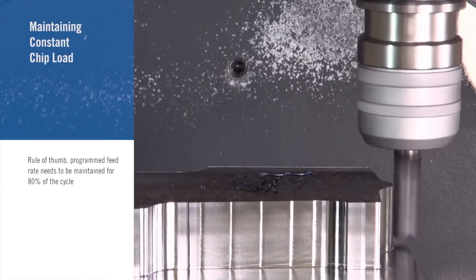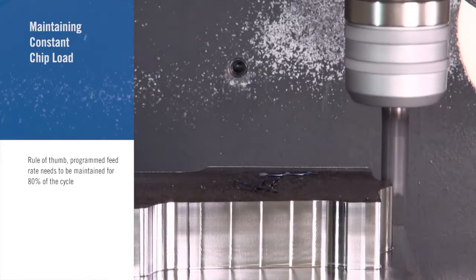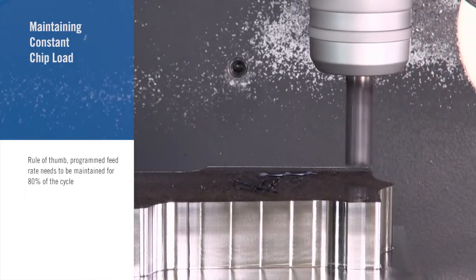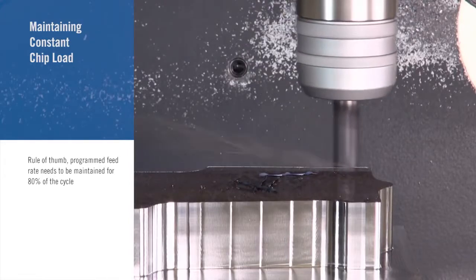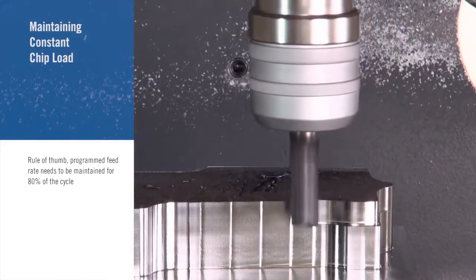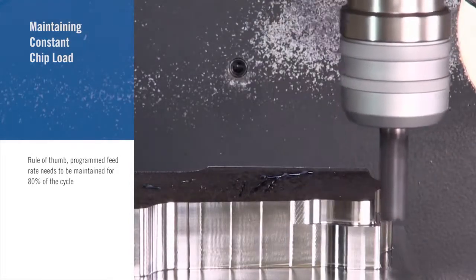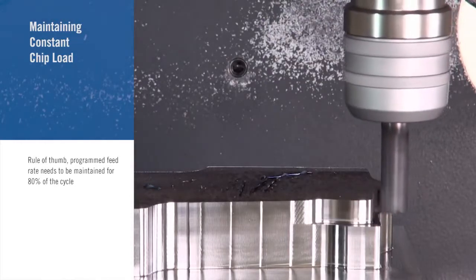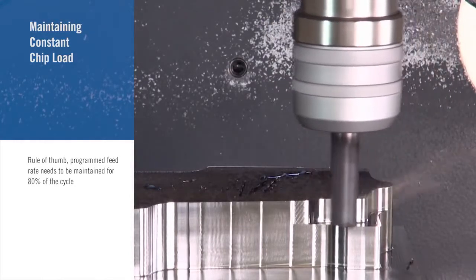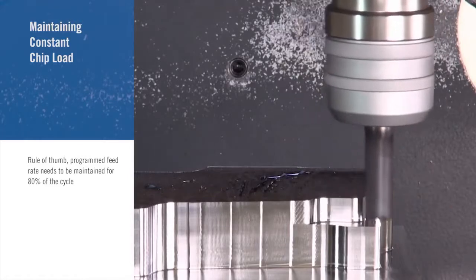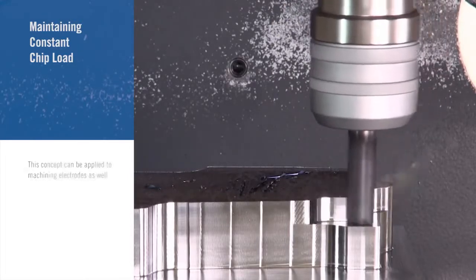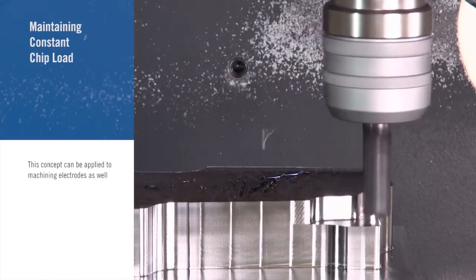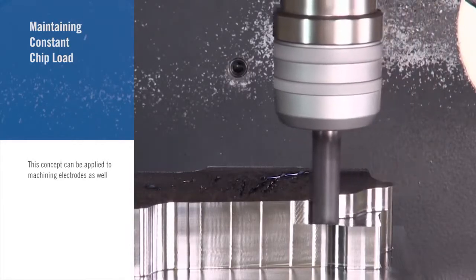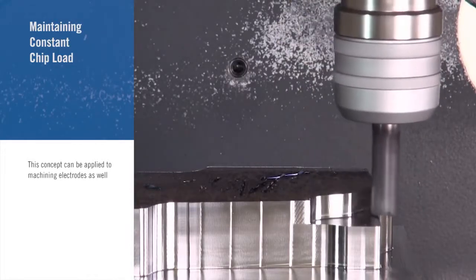For example, if you're running a 30,000 RPM machine, you program for 300 inches a minute, but the machine can only maintain about 150 inches a minute for 80% of the cycle, you reduce your RPM to 15,000 so you maintain a more constant chip load. You can have a huge increase in tool life with a very, very small difference as far as cycle time goes. Now, this concept doesn't just apply to hard milling, it also applies to machining graphite electrodes too, so keep that in mind when you're machining your electrodes.